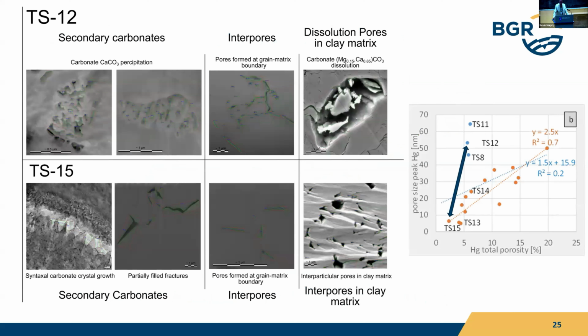So we did a detailed SEM study at the University of Greifswald that was done by Tobias Menzel. And he compared, as an example, TS12 and 15. The 15 is following the trend. Pore size is much, much smaller, and the porosity is similar. So what we could see, and that was quite difficult to resolve, is that in these small pores, which are on the left side, this is basically the size we have to consider, like 50 nanometers, something. We could see that there are some carbonates precipitated there, and other pores were completely filled with carbonates. So obviously, this relation, the mercury total porosity and the mercury pore size, can be affected by cementation.